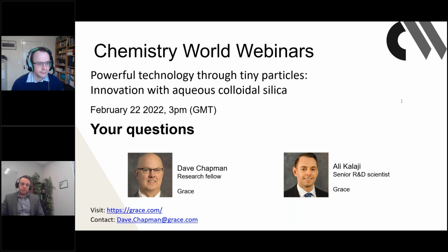Right, so Dave mentioned the pH is a very important factor. As you change the pH, you're actually changing the charge on the surface, and so you're able to change the pH up to a certain point, but there are certain regions where colloidal silica is just unstable unless you do a surface modification and use a different grade, as Dave mentioned. And another very important consideration is the presence of any high ionic strength, and in particular any multivalent ions in solution.